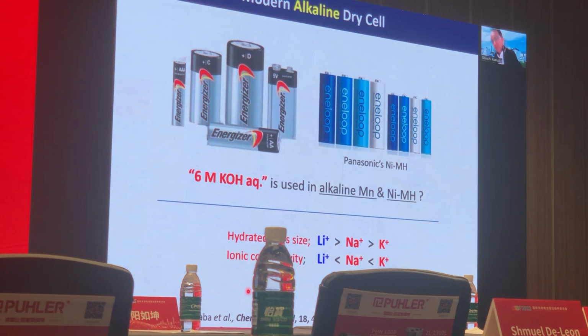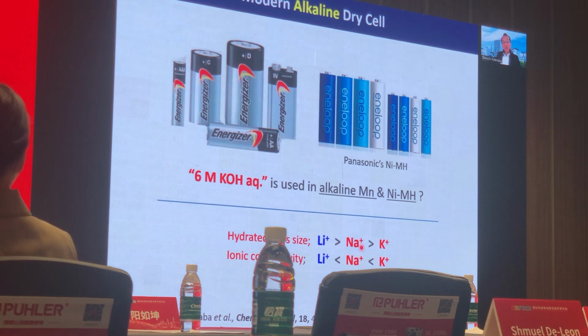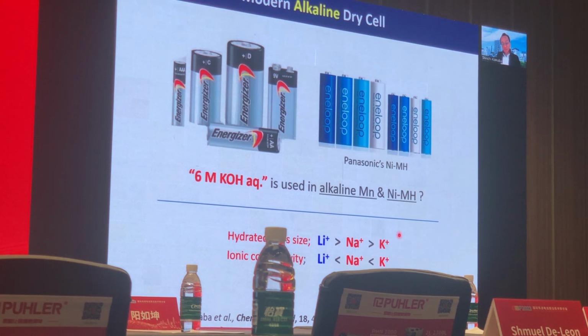A recent alkaline cell, like the manganese cell and the nickel metal hydride cell, is filled with 6 molar potassium hydroxide aqueous solution, which shows the highest ion conductivity for an aqueous battery cell. So why potassium? Because potassium shows a smaller size than lithium and sodium in hydrolyzed condition. And after dissolving lithium, sodium, and potassium salts, the highest conductivity is achieved by using the potassium counterpart because of the smaller hydrolyzed ion size. So potassium or sodium are essentially advantageous over lithium in terms of ion conduction and also higher transport number in liquid electrolyte solution.